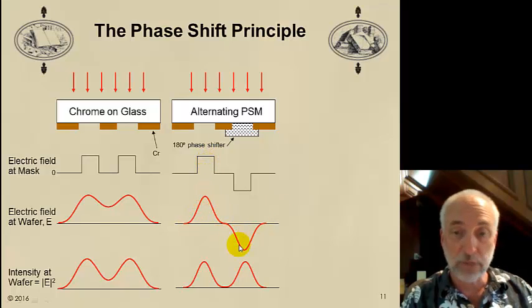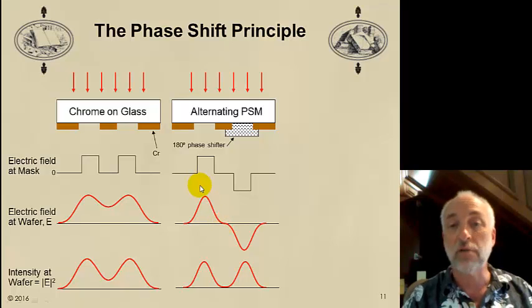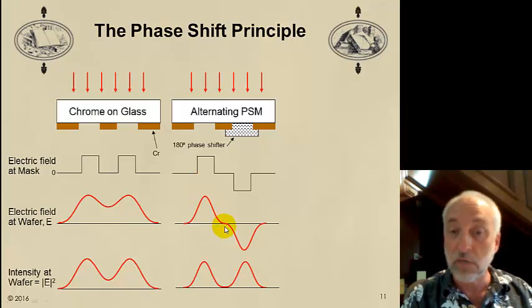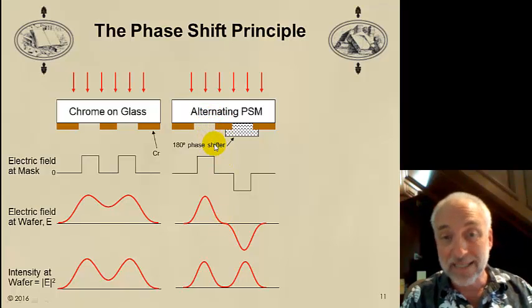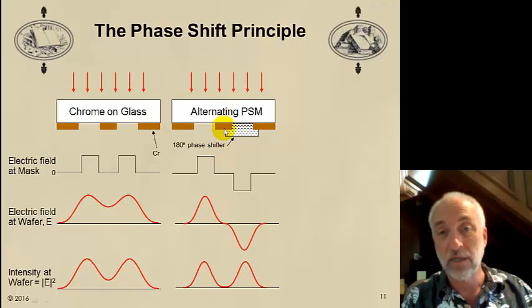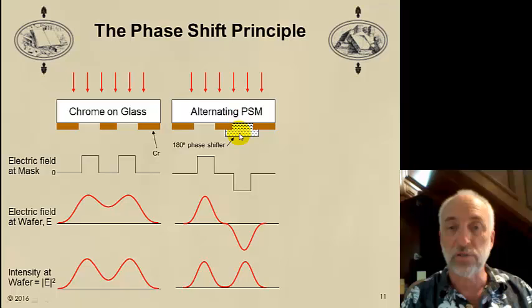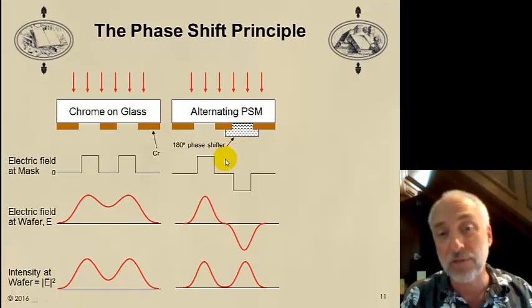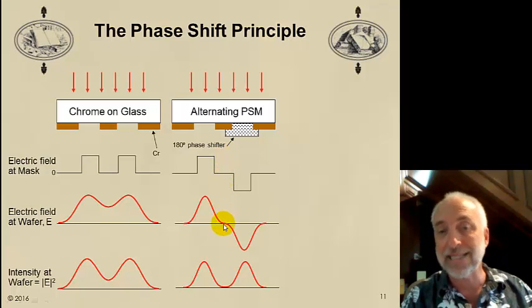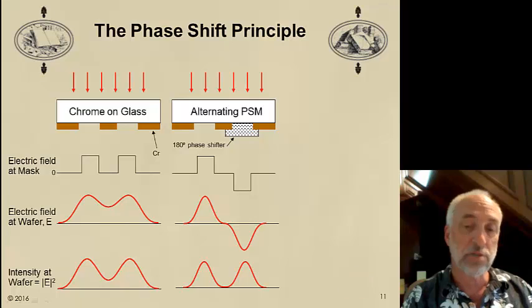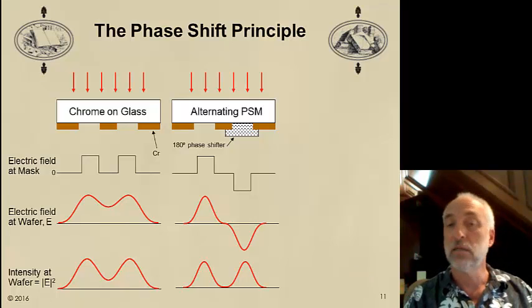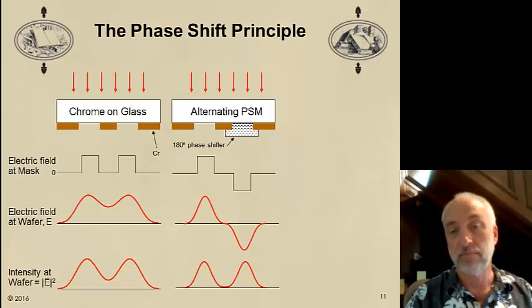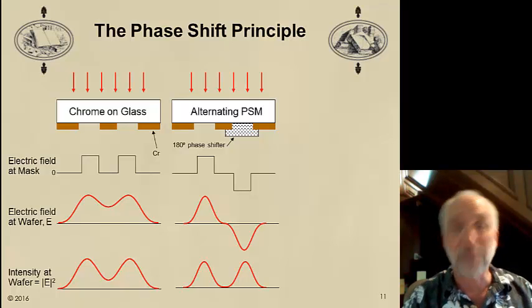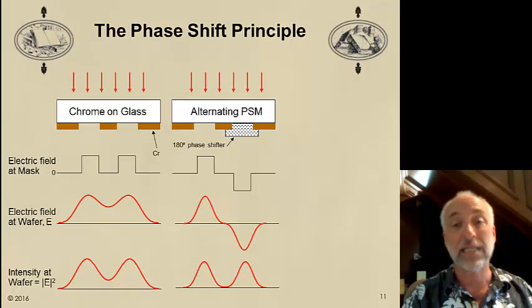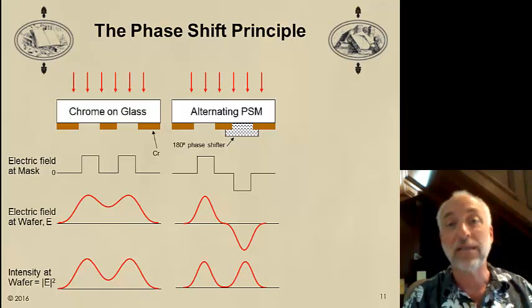Now the electric field at the wafer is going to look something like this, and you see that it has to go through 0. To go from plus to minus electric field, it goes through 0. In other words, the light that's diffracted from one space coming underneath the chrome line in the middle exactly cancels with the 180 degree phase shifted light coming from the other space that diffracts underneath the chrome line, so that I get 0 at the wafer. 0 electric field produces 0 intensity, so now I have a small chrome line that is darker because I have a phase shift on one side of it compared to the other side. That's called an alternating phase shifting mask because we have this 0, 180 degree on the spaces alternating or surrounding that small chrome line.